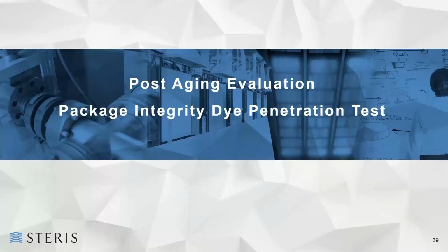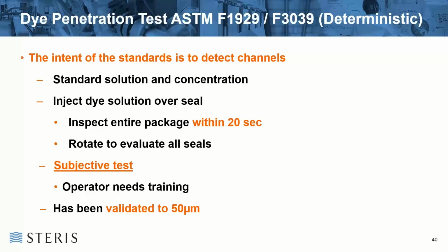The likes of dye penetration testing is an excellent test which will show you very, very quickly what is happening with your seals. Depending on which test you're using, the likes of the ASTM F1929 standard will look at all your seals. It'll give you an answer to see if you have any channels in the seal or any openings in the seal in less than a second. And you can do a complete test within 20 seconds, depending on the size of the actual product. The larger the product, the longer it's going to take. The problem with it is that the